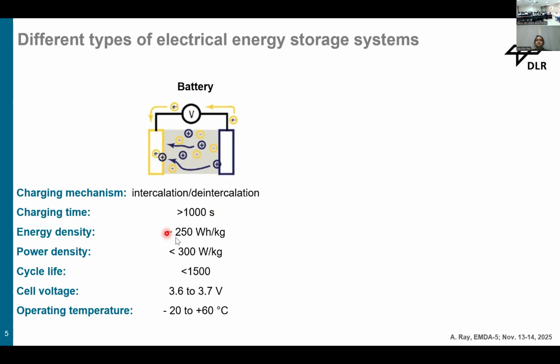Energy density is around 250 watt hour per kilogram, and power density 300 watt per kilogram. Cycle life is 1500 cycles. You can imagine that in real life. Whatever mobile phone you have in your hand at the moment, after 3 or 4 years you cannot expect your battery to run for longer times. So that's 3 years, 4 years, or a maximum of 5 years.